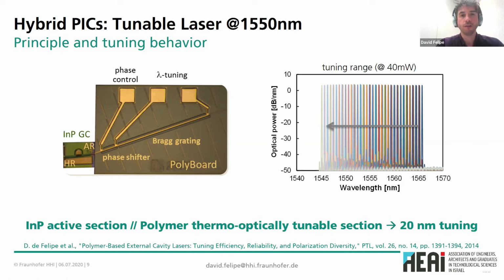And also, the polymer material typically shows a very low thermal conductivity, meaning that if we generate heat on it, the heat will remain close to the waveguide and therefore will not be dissipated, which allows us to have a very efficient tuning mechanism on the polymer technology. And you can see here on the right-hand side that for this 20 nanometer tuning, we need a power of more or less 40 milliwatts.